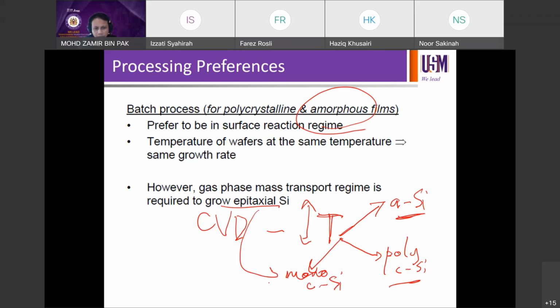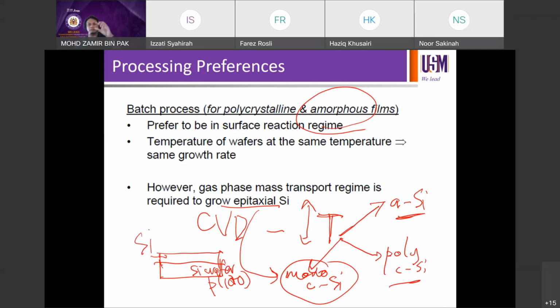If you talk about epi process, then you can actually get monocrystalline silicon, especially if you already have a silicon wafer, say P100 monocrystalline, right? And then you can run your CVD process to deposit a thin film of silicon. Silicon juga, tapi thin film. For example, 50 nanometer, perhaps for a specific purpose in the device fabrication. But you want that 50 nanometer to be monocrystalline. Boleh, that can be done because you can run that at a certain temperature, especially high temperature.